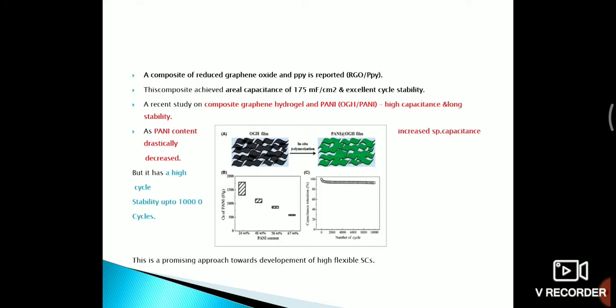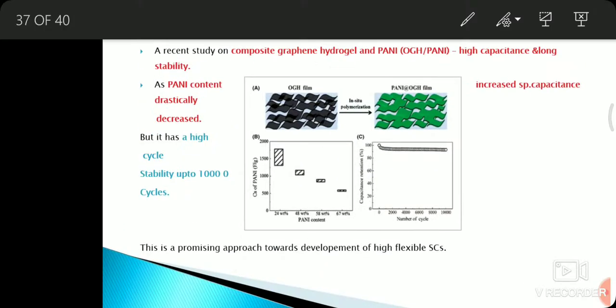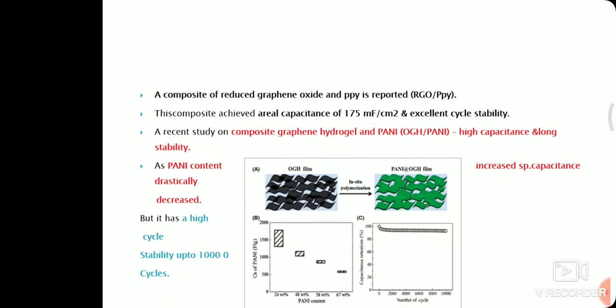The recent study on composite graphene hydrogel and polyaniline, that is OGH PANI composite, high specific capacitance and long cycle stability is obtained. In this OGH polyaniline composite, as the content of polyaniline increased, the specific capacitance is drastically decreased. But it has a high cycle stability up to 10,000 cycles. That is shown in the figure. That is, as the content of polyaniline is increased, we can see a drastic decrease in the specific capacitance, but the capacitance retention is constant even after 10,000 cycles. So this is a promising approach towards the development of high flexible supercapacitors.